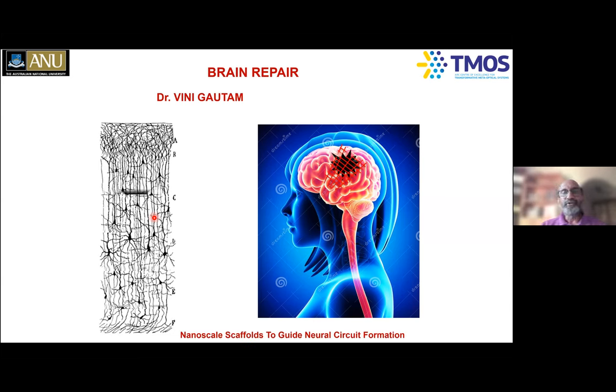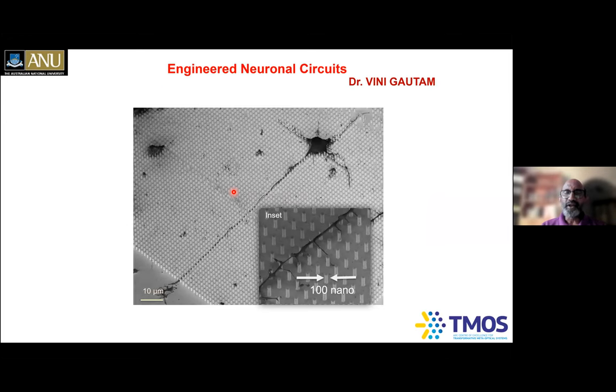Vini Gautam spent more than 2 years optimizing various protocols and getting the conditions right. Here is a case of a neuronal cell grown on indium phosphide nanowires; you can see the many nanowires in the close-up. These neurites or axons follow these patterns beautifully. You can see the dendrites coming from these axons also following the topographical features of the nanowires. Instead of a single neuronal cell, what happens if you use multiple neuronal cells?